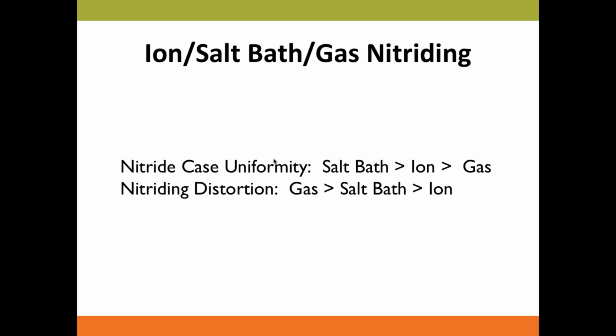And then distortions are based on temperature. When you put the steel back at high temperature, there's a danger of distorting the steel. Since gas would have to use the highest nitriding temperature, the distortion in gas potentially will be the highest. The second one is the salt bath, and the lowest one will be the ion, because with ion you can have a low temperature of the steel and use plasma to activate the nitriding process.